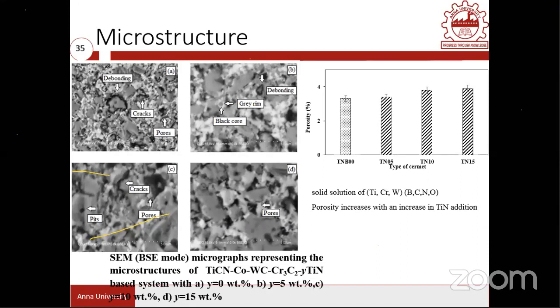And what is the effect of varying TiN addition here? The porosity level is increasing. That means the more TiN, the more nitrogen is removed from this source during sintering. Wherever the nitrogen is removed, even in vacuum conditions, those places still act as pores or pits, and the porosity is really increasing here. That is a bother.